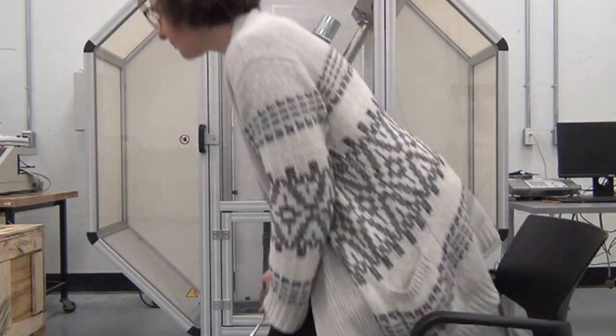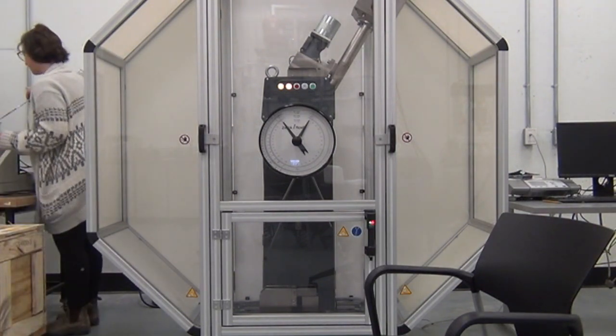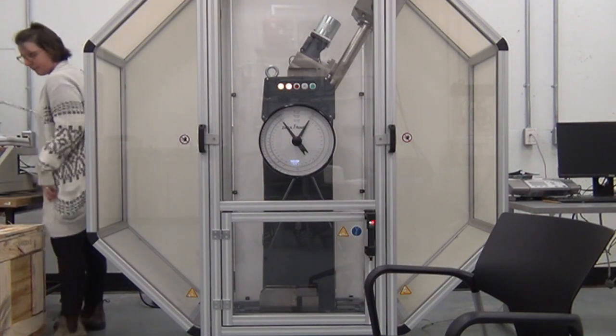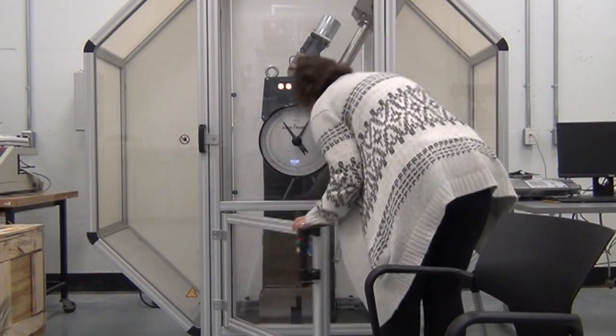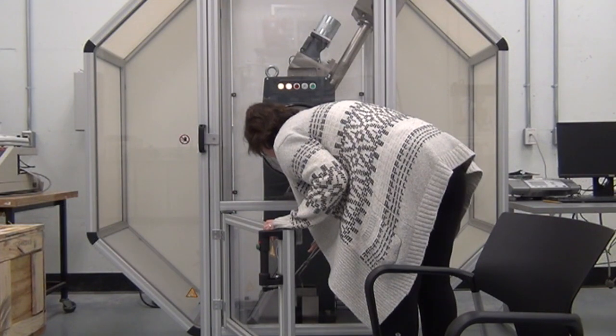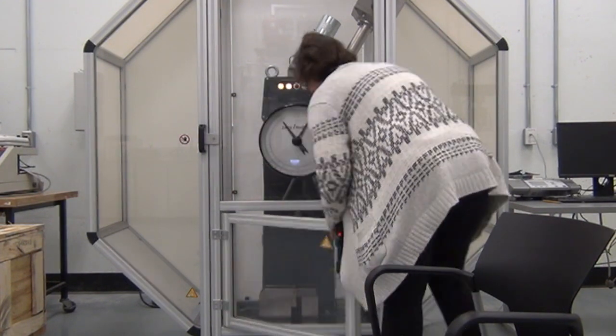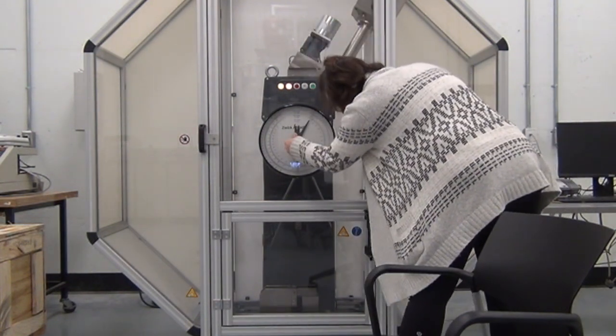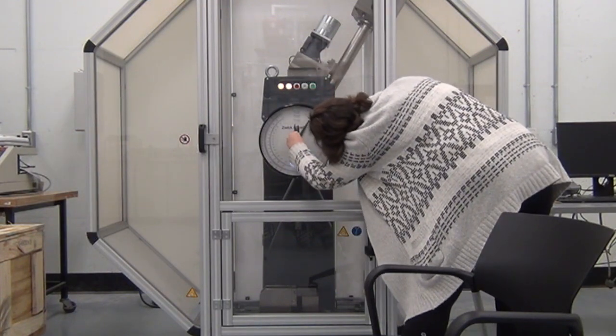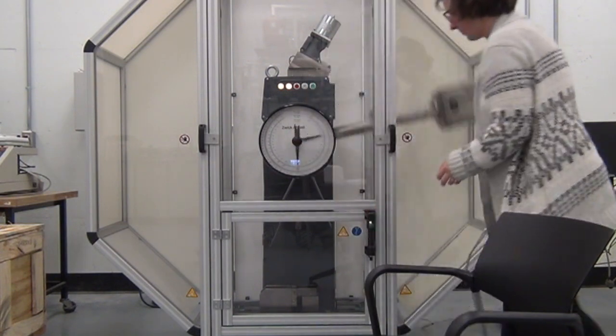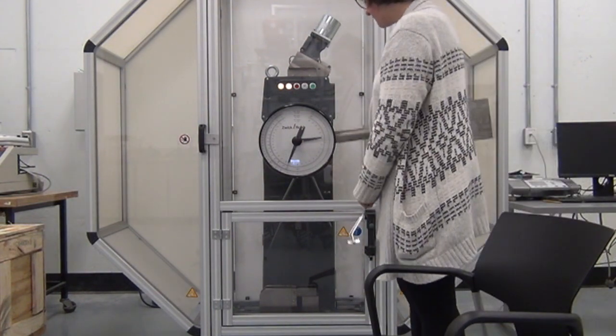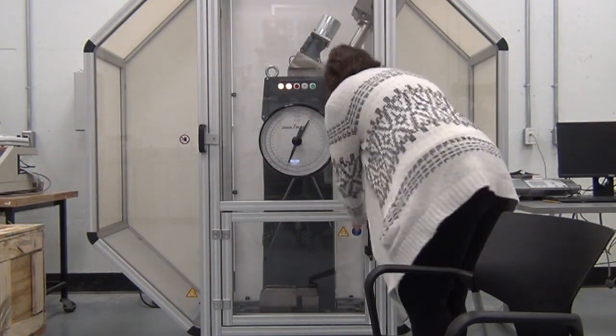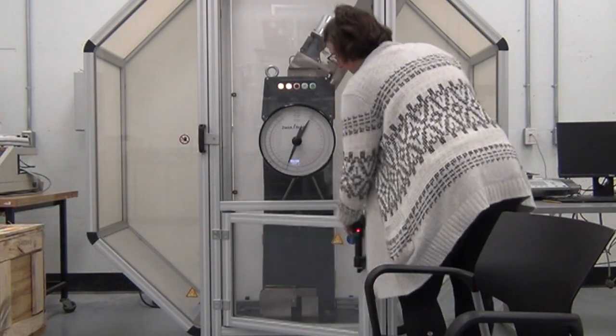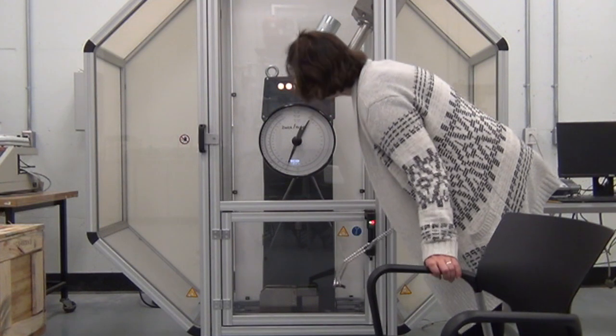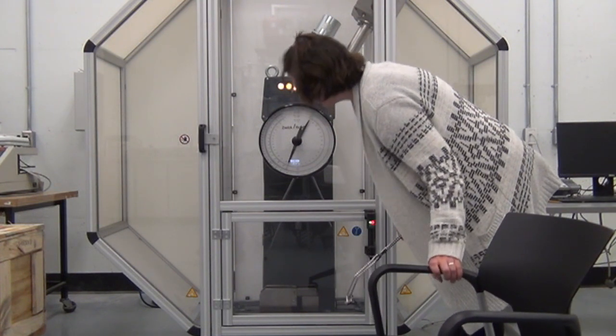So the last sample we're going to do is the boiling water sample at 100 degrees Celsius. So I'm going to go pick that up with the tongs. And I'll place it in the machine. And I want to run the machine as quickly as I can here, just so that I don't lose too much heat from my sample. So I can retrieve my sample again. And I see that I have an impact energy of around 145 joules.